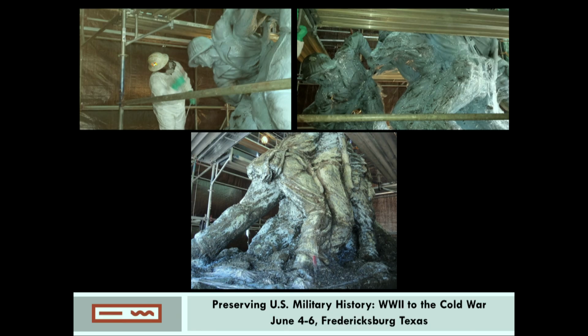So we began with the coating removal. There were 2 separate phases of this. In the first phase, we used a water-based paint remover to get those 11 layers off. This was Sea to Sky. The details are in the paper. The name of it is Sea to Sky. And it was applied in numerous sequences because the paint was so thick, and then it was washed off, scraped off and washed off by a pressure washer.